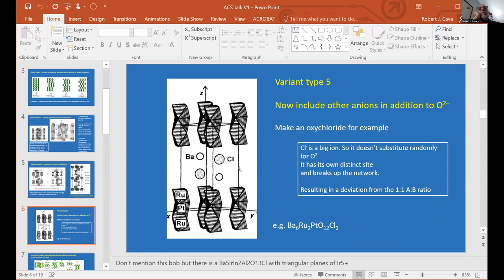You probably don't know it, but one-dimensional chains of magnetic atoms can have particular electronic structures that can be calculated and understood. But when you start breaking up the chains, well, that's interesting in itself. But you can also use solid-state chemistry to start breaking the chains up. And here's an example of a barium, ruthenium, platinum oxychloride, where the ruthenium and platinum form an ordered trimer.